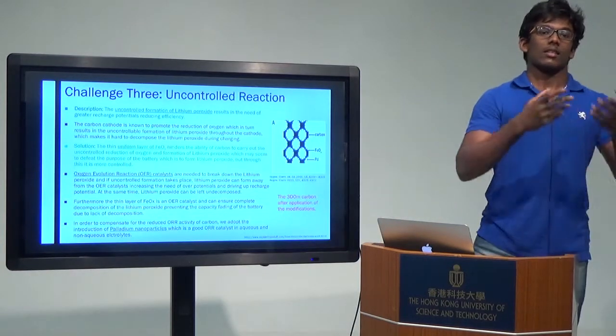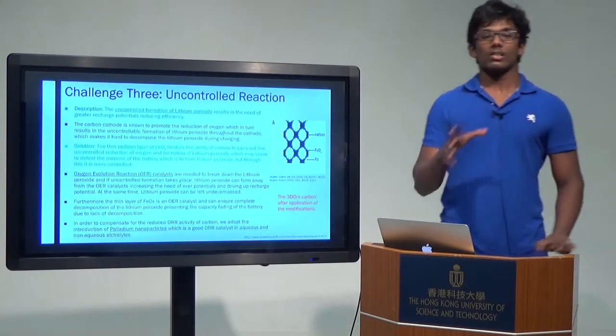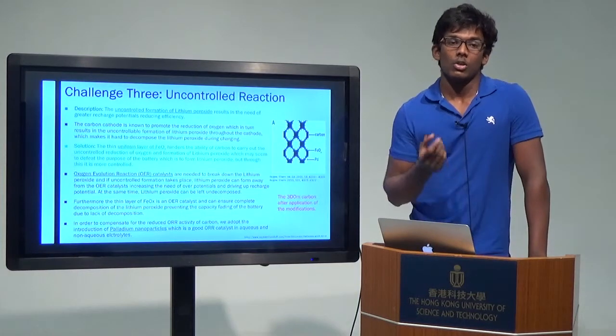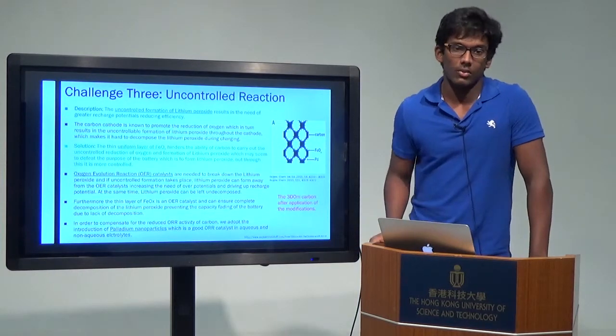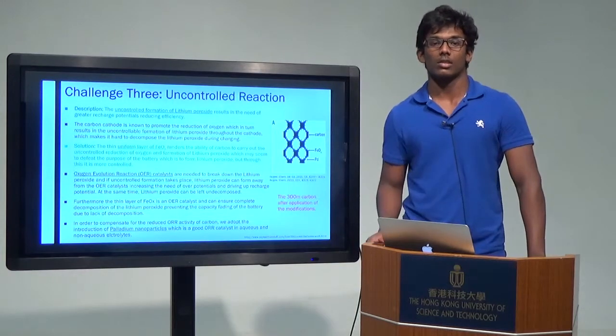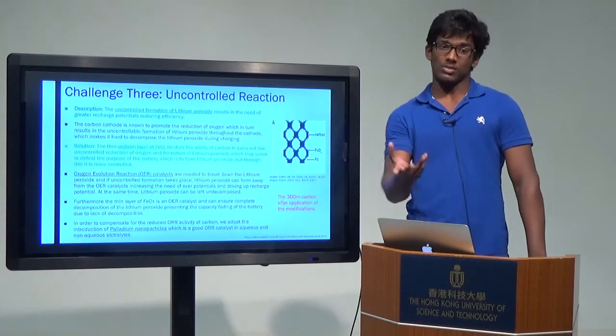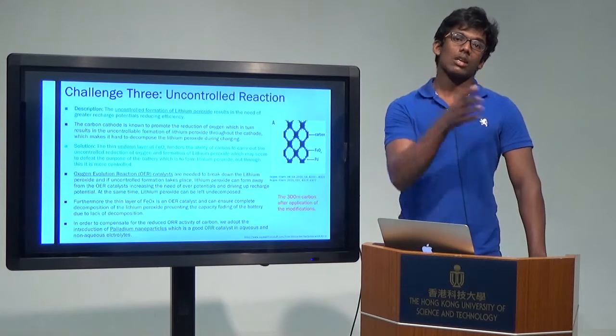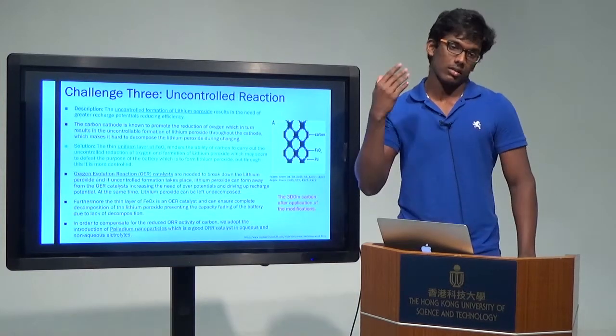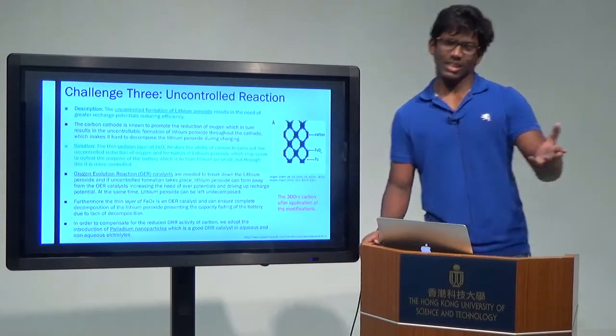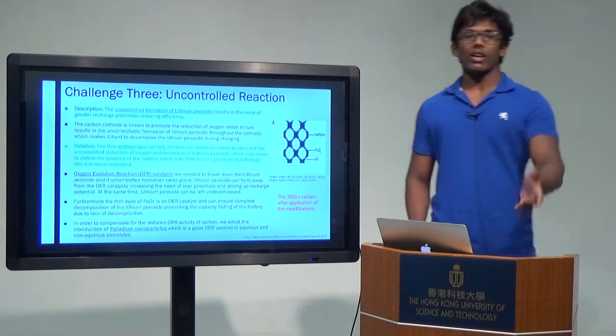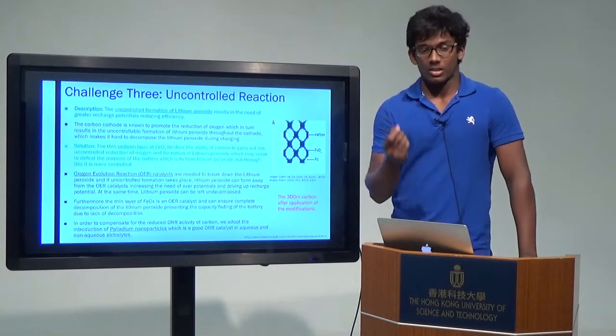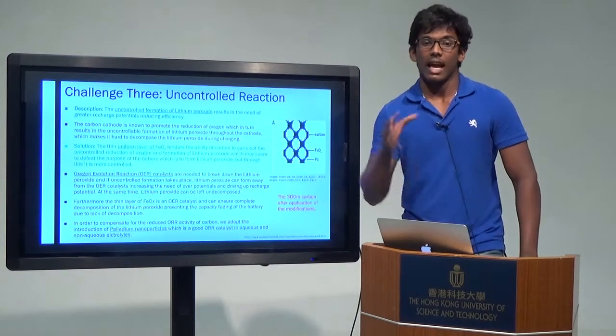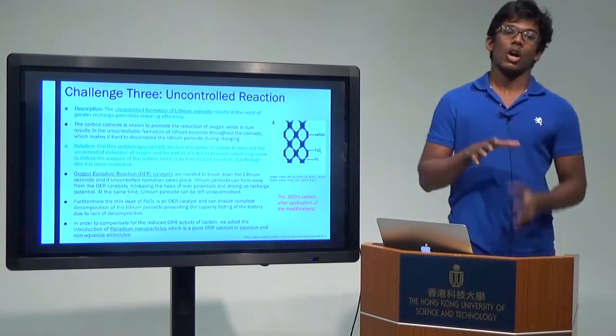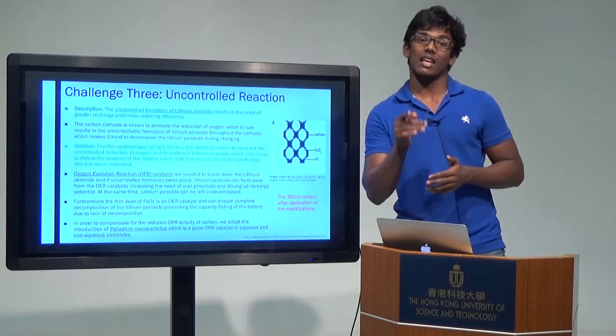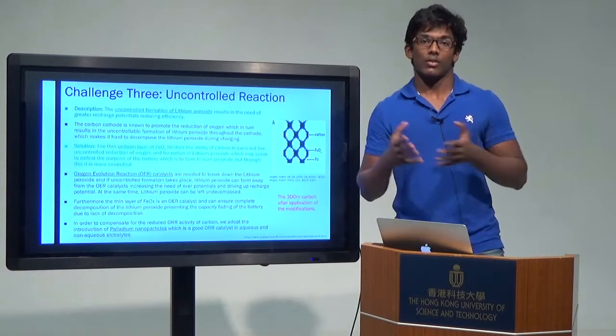So once again, what our solution is, the iron oxide will hinder the ability of carbon to carry out the uncontrolled reduction of oxygen and formation of lithium peroxide, which may seem to defeat the purpose of the battery. However, this actually controls the reaction progress. Once again, iron oxide is an oxygen evolution reaction catalyst and can ensure the complete decomposition of lithium peroxide, preventing the capacity from fading due to lack of decomposition.